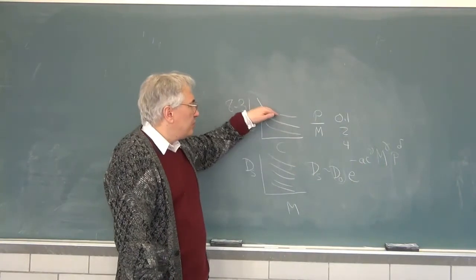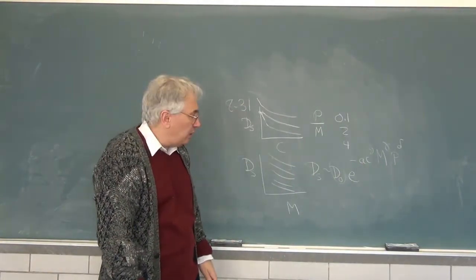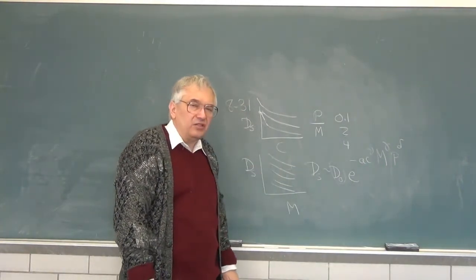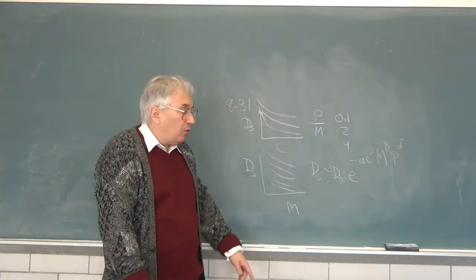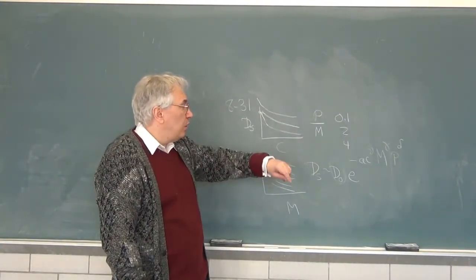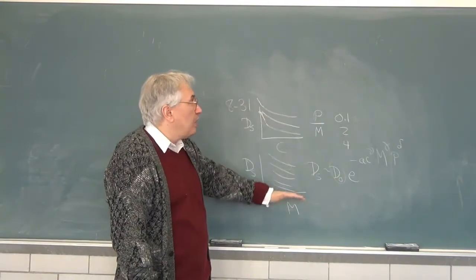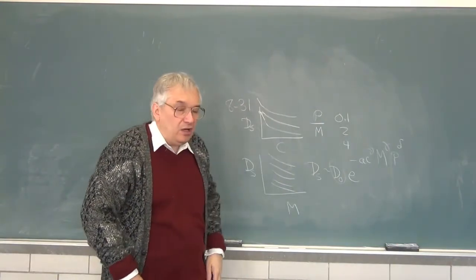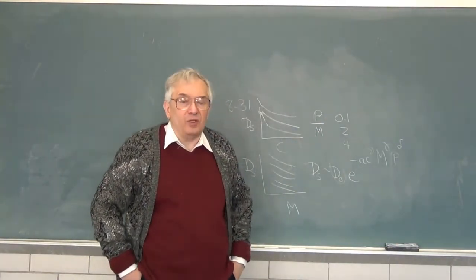The concentration slices work extremely well. The molecular weight slices do not work as well, but one function and a very small number of parameters describes an extremely wide range of probe and matrix molecular weights.